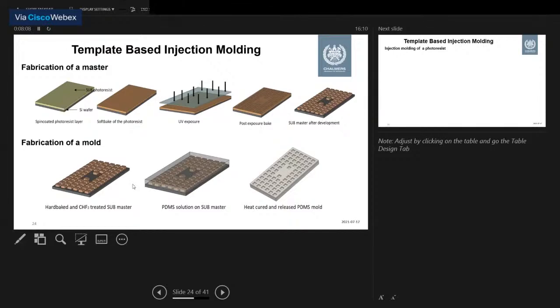By using this master, we fabricate a mold. But before using this master as a mold, we treat it with CHF3 to make the master non-stick. And we use PDMS to fabricate the mold. Once we pour the PDMS on the master, we degas it, and after heat curing, we can easily remove the PDMS mold because the master is already a non-stick material. So in this image, you can see how a PDMS mold looks. It has the opposite structure of the master.